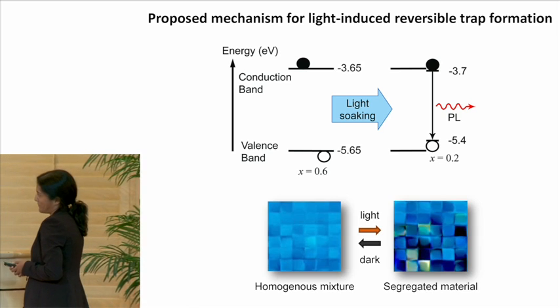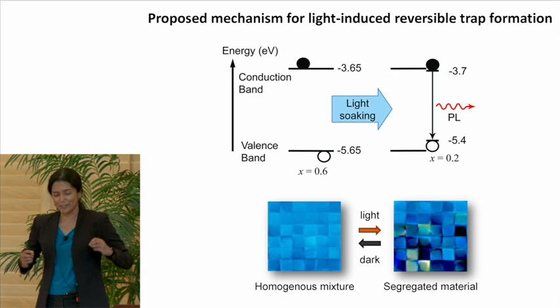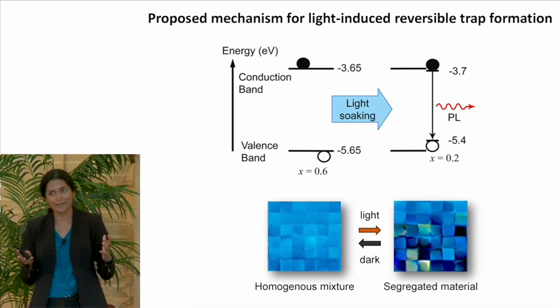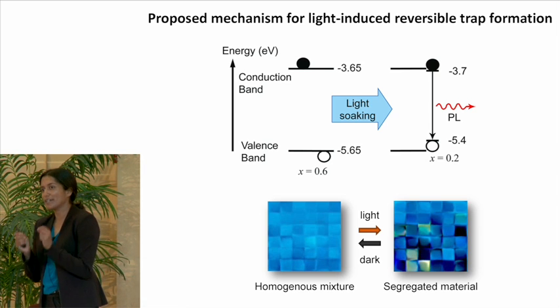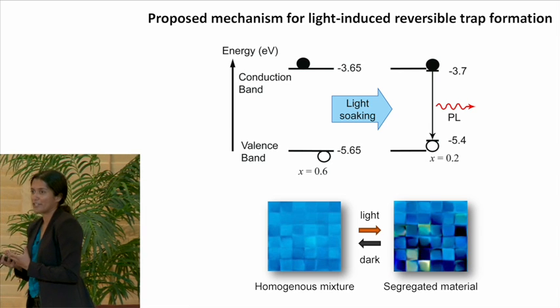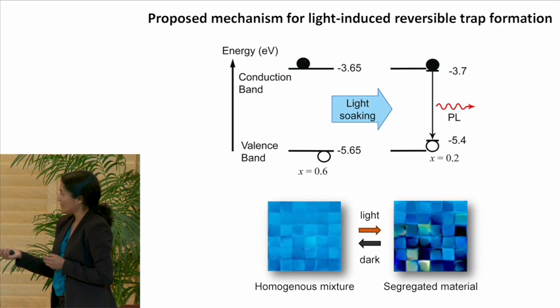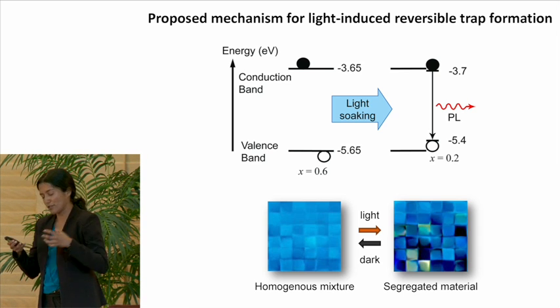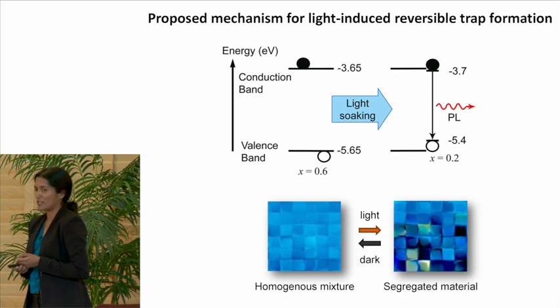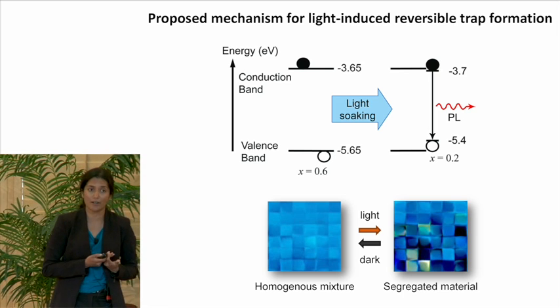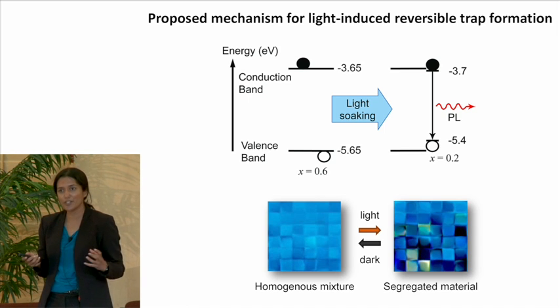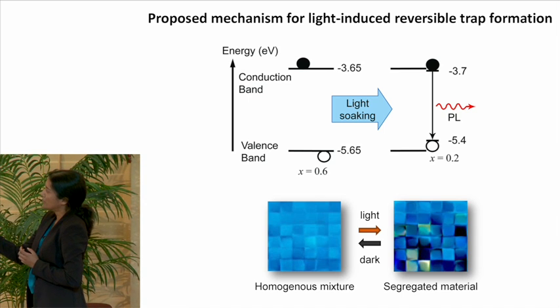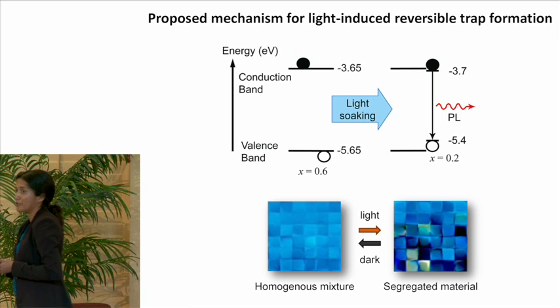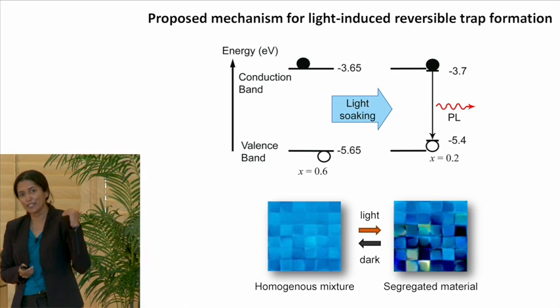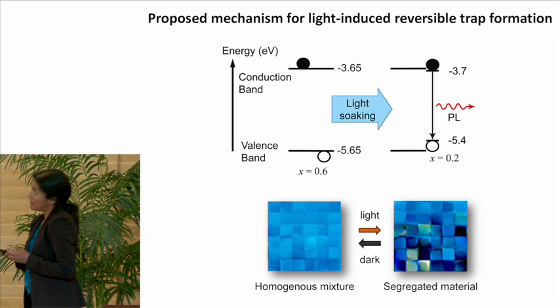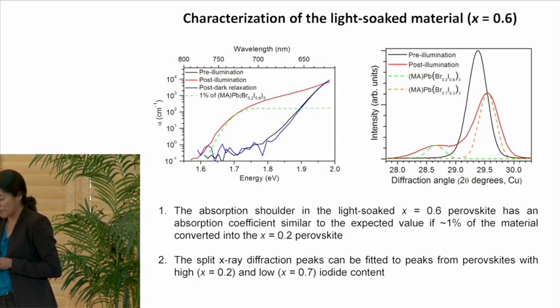So our speculative mechanism can be summarized by this picture. We have this homogeneously mixed bromide iodide lattice, lead bromide iodide lattice, but when we shine light on this material, there's halide segregation that is initiated by the illumination. And here my darker blue squares show areas of higher iodide content, and these lighter blue squares show areas of lower iodide content. So there's halide segregation under illumination, and all the holes, of course, will move to the lower energy material, which is the iodide-rich material. And therefore, we get photoluminescence only from that trap. And our data so far support this speculation.